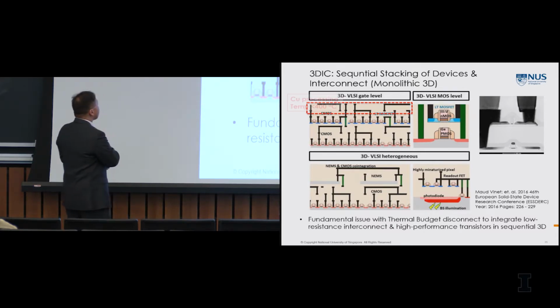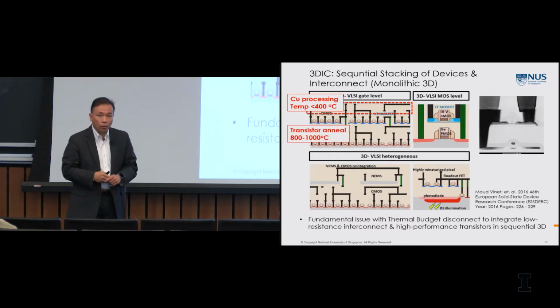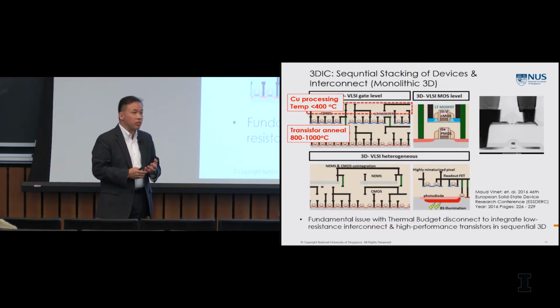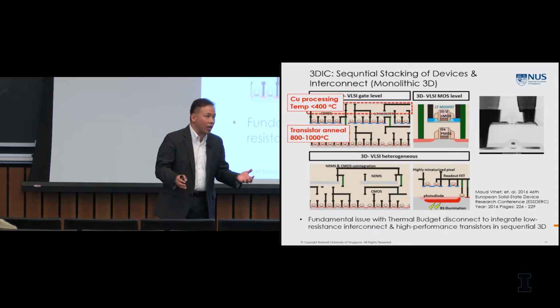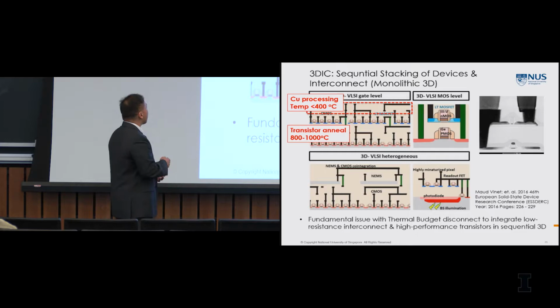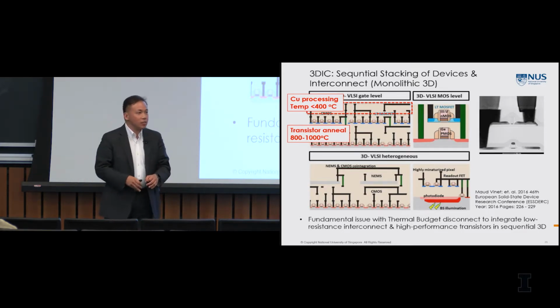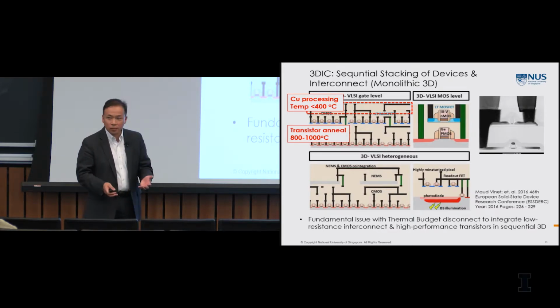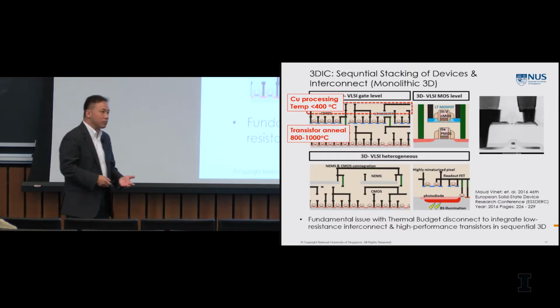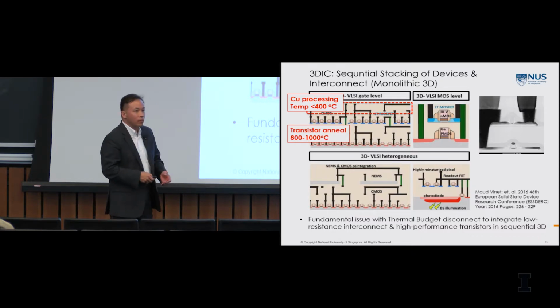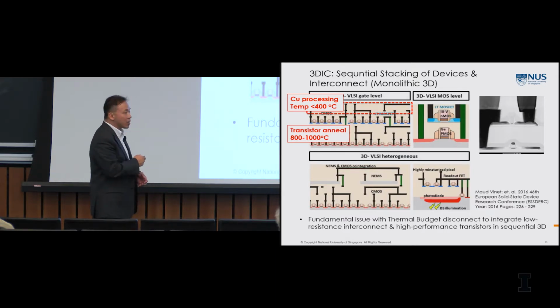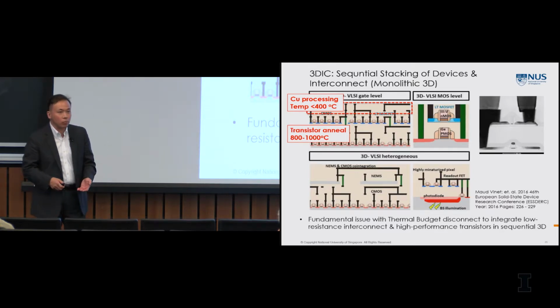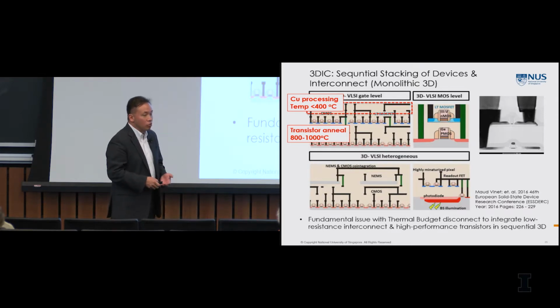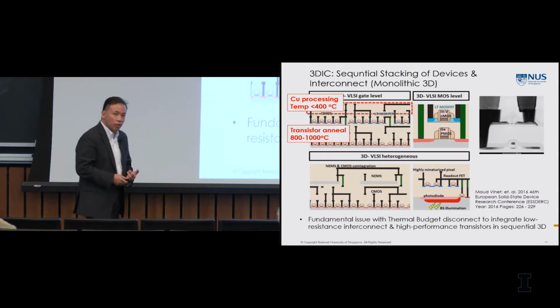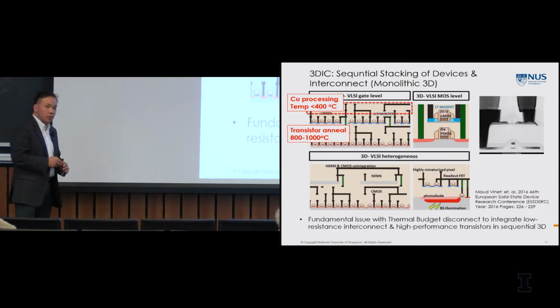But there's a problem. There's a problem as follows. In advanced interconnect made out of copper, the processing temperature cannot be greater than 400 degrees C. And the reason for that is because copper will out-diffuse into the low-K dielectric layers and mess up your entire circuit, right? Transistors, at least silicon, like to be processed somewhere around 800 to 1000 C, because that's where your dopants are activated, and that's where your defects are annealed. So there's a problem. If you want to build transistors on top of interconnect, which is the dream, basically the interconnect has to be able to tolerate higher temperature, or your transistors have to be processed at much lower temperature. But processing transistors at lower temperature basically reduces their performance, because you have defects and the dopants are not activated. Okay, so that's one major issue that people are trying to overcome.